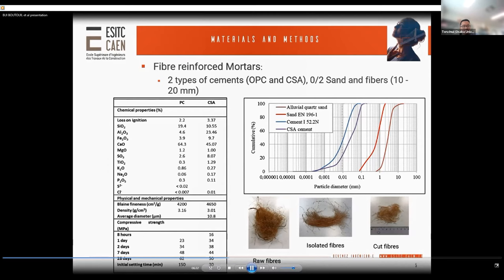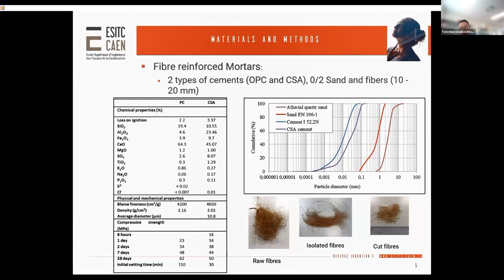As you can see, calcium sulfoaluminate cement contains approximately 55% of calcium sulfoaluminate, and it is considered to some extent as an eco-friendly binder. We can also see that calcium sulfoaluminate cement is reported as a special cement with a lower alkali content. Therefore, this cement could help reduce the degradation of natural fibers in the mortar composite.